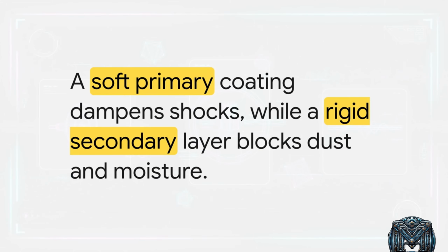We actually apply this in a highly deliberate dual-layer strategy. There's a soft primary coating that acts like a shock absorber to dampen mechanical vibrations so the fiber can bend. Then, a rigid secondary layer acts as armor against dust, moisture, and microscratches. This specific coating strategy allows the pristine silica glass underneath to retain its inherent 2 million psi tensile strength. Crazy as it sounds, if kept absolutely pristine, that glass is actually stronger than steel under tension.